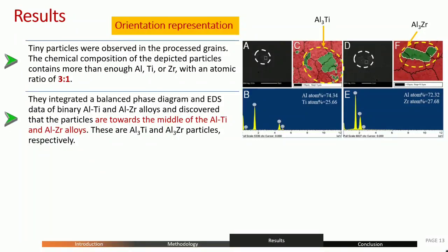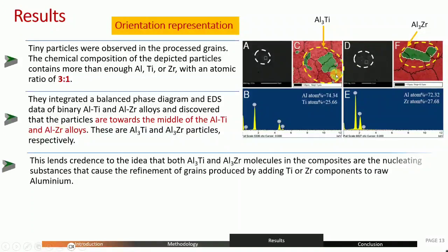So what I discussed earlier, that we want this grain refinement to be in the middle of the melt, inside the middle of the entire melt. So they have found that they are able to achieve Al3Ti in the middle of the melt. This is the requirement: grain refinement in the entire volume of the matrix. Matrix is basically the aluminum, and inside that we are not only having grain refinement at the surface where heat exchange is there, but also in the middle of it. So this is their achievement, this is what they have reported here.